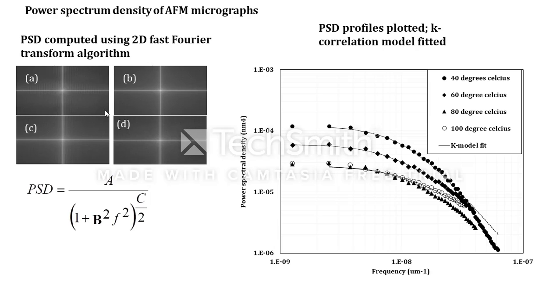And this is the key correlation model. It can be seen that the PSD decreased with temperature. The highest is at 40 degrees, and the lowest is at 100 degrees. So the value of B, which measures the spectral length, decreased with temperature; inhomogeneous lateral roughness at higher temperature.